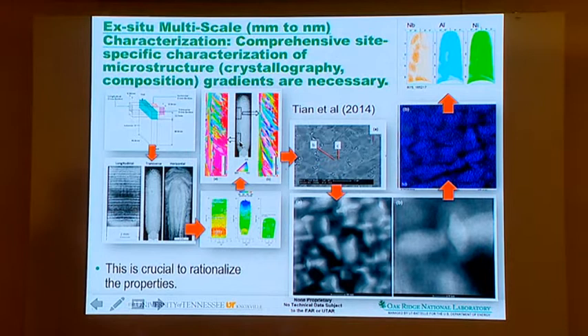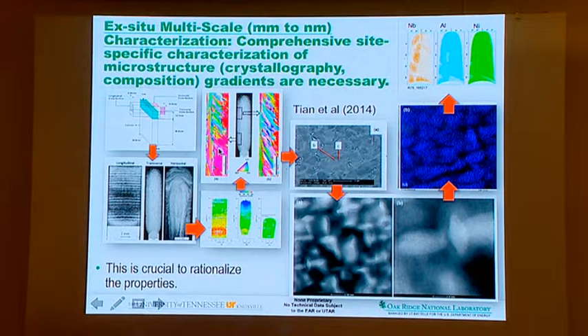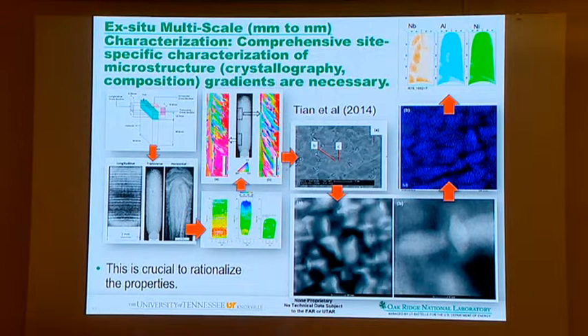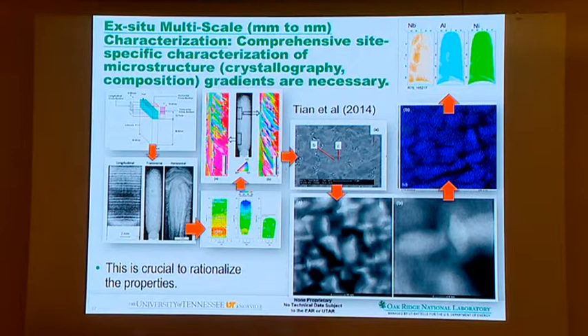What you notice here is the texture of a face-centered cubic structure, not the BCC; it's an FCC structure. Red means they're all aligned in the 001 direction. As you go up, you can see other colors showing up, which means the crystals are misoriented with reference to the build direction. And we know why that happens.